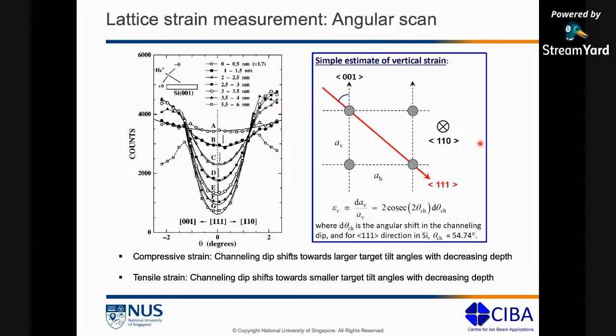So in fact, there is even a formula for that. So this is the same set of curves I showed you before. And the angular shift in the channeling dip. So this is the channeling dip, right? So the angular shift that goes from here all the way to here is what will give us an estimate of the lattice strain. Okay, and then of course, if the dip shifts towards a larger tilt angle with decreasing depth, that gives us compressive strain.